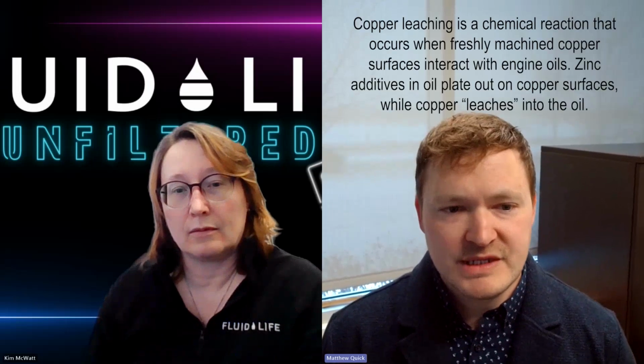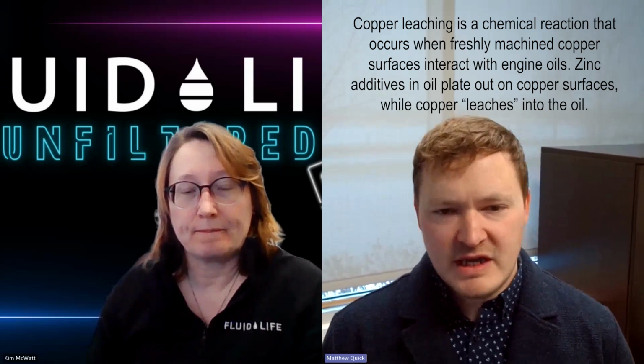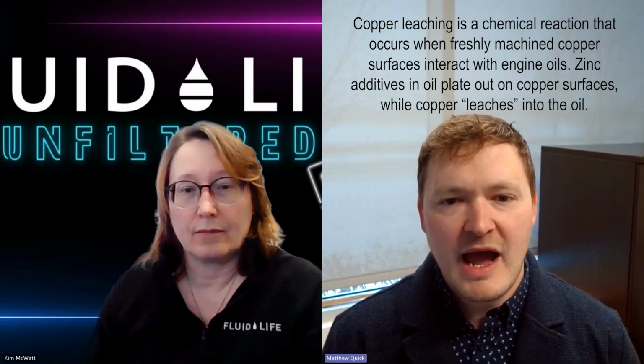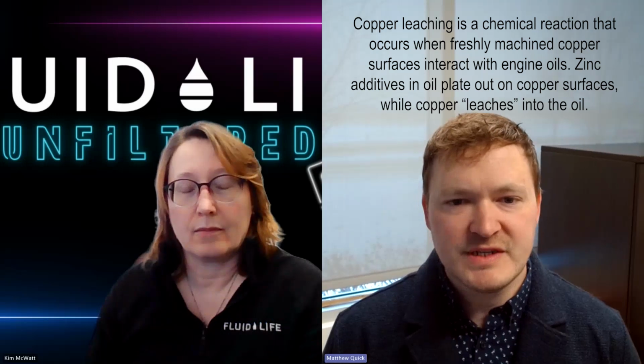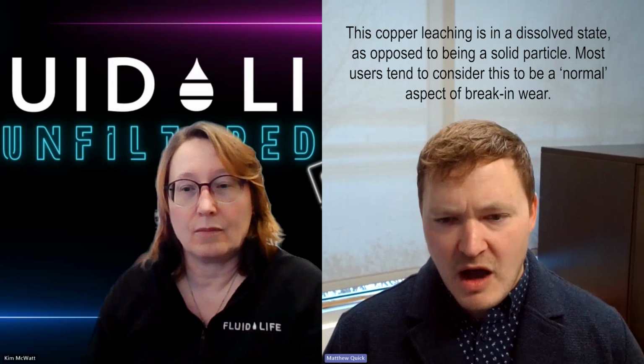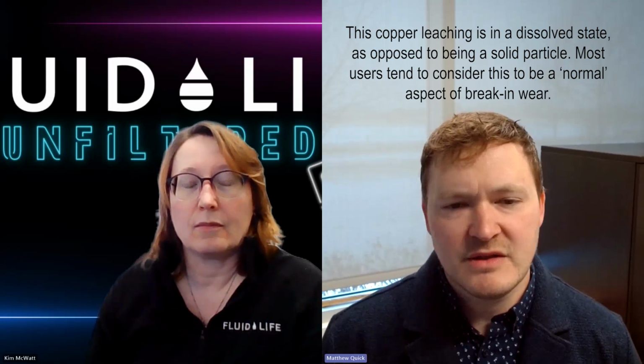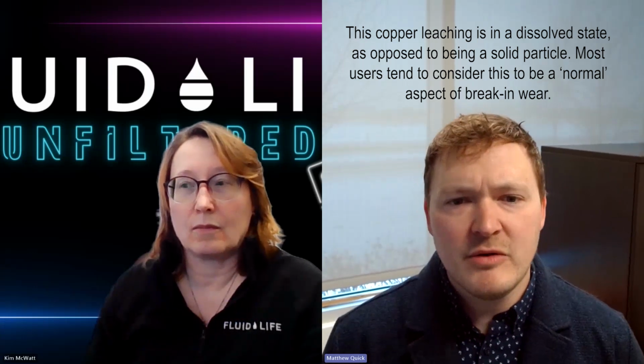So when it comes to copper leaching, what are usually the sources of copper leaching? Right. Great question, one that we get a lot, actually. Typically copper leaching happens to new components, like new engines. In essence, it's when the ZDDP additive, the anti-wear additive in the oil, interacts with copper surfaces, typically on coolers. That somewhat erodes and dissolves the surface of those components, and it brings that element into suspension in the oil. So you start to see really elevated levels of copper in normal conditions. Sometimes the copper can be in the hundreds, 500, 600 parts per million, when we detect it using the ICP in a routine analysis sample.